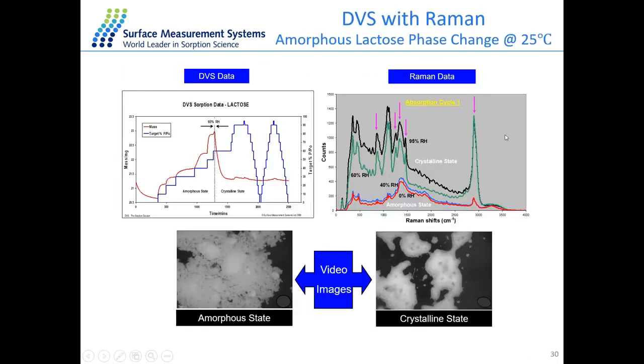In this example, we're looking at the DVS with Raman and looking at the amorphous lactose changes at 25 degrees. So this is the typical DVS data that we've obtained. We've introduced a drying stage here and introduced different levels of relative humidity for our sample over time. And we've actually done 2 cycles. So this bit here is our absorption and desorption. So that's cycle 1. And again, absorption and desorption, cycle 2.